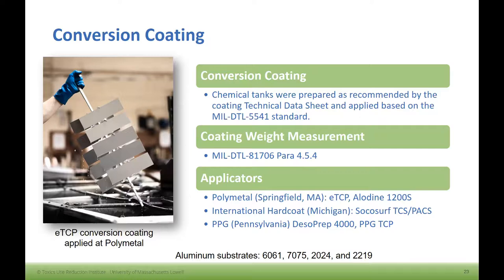This time we had a more comprehensive alloy assortment: 6061, 7075, 2024, and 2219. They go from left to right in increasing amount of copper content. The more copper there is in the aluminum alloy, the more difficult it is to get the corrosion protection that you need. So by including the 2219, we were really pushing the limits for corrosion protection.